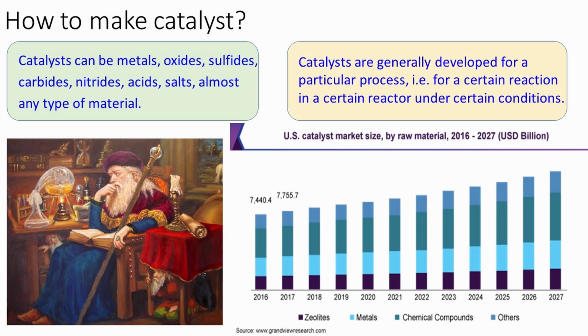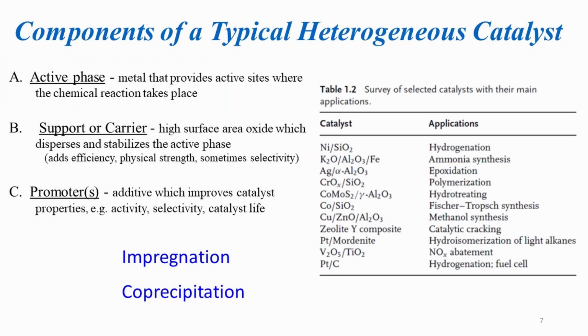Solid catalysts dominate in industrial catalysis, in view of the large-scale applications such as ammonia synthesis for fertilizers, oil refinery for transportation fuel, petrochemicals, and environmental catalysis. The most important class of solid catalysts are the so-called supported catalysts that often consist of supports such as alumina or silica. The active nanoparticles of this catalyst can be metal, metal oxide, or metal sulfide with a size of 1 to 20 nanometers.